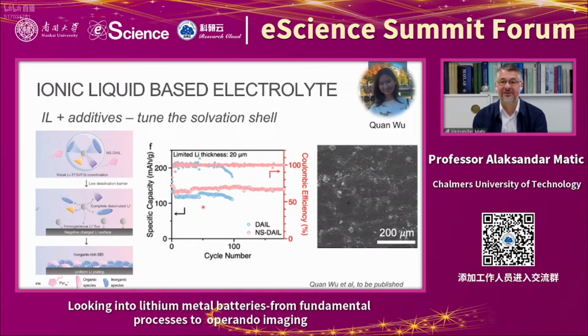But I just want to share with you that with her new electrolyte formulation here, you get extremely stable cycling with good capacity. This is in a LFP lithium metal cell, but it's a lithium metal cell with very limited thickness of the lithium electrode. So these are very harsh conditions. And still the cycling looks very good and with a very high Coulombic efficiency. And you can also see on the SEM image how smooth a surface you get.